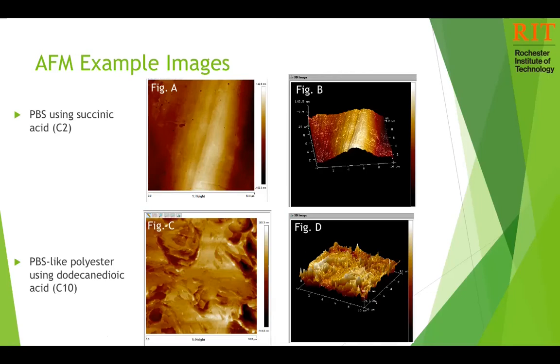Here are some example AFM images taken from the hot pressed films for PBS and a PBS-like polyester using dodecanedioic acid. You can view the 2D images in Figures A and C, respectively, and their corresponding 3D images in Figures B and D. Notice the color grading of the image indicates the relative height of the surface topography. Also note that the PBS-like polyester in general appears rougher than the PBS film.